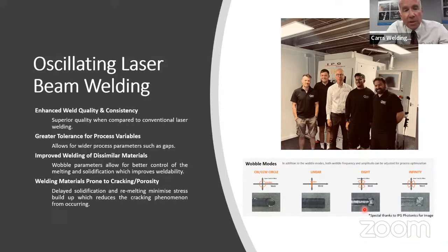The wobble welding, as they call it, we like to call scanning, where you scan the weld beam across the width of the weld, and you can have various different shapes, but generally speaking, we use pretty much a circular shape in most things, sometimes a linear straight. This basically allows you to control the depth and the shape of the weld, and it's really nice in non-ferrous materials. Basically, it's just more controllability and repeatability when it comes to the welds. And with some welds, you want a preheat and post-heat, and with some dissimilar metals, you can do that with an oscillating beam.